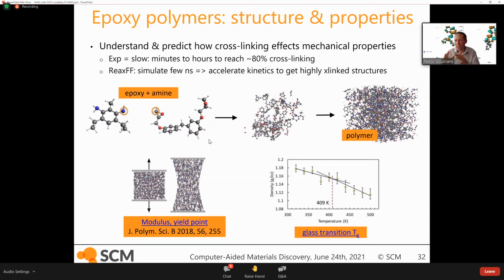And typically what you get out of that are pretty good cross-linking densities, and the mechanical properties, things like glass transition temperatures, are pretty good. So you can use these bond tracking or bond boost simulations to design different curing agents to get, for instance, higher densities or polymers with higher glass transition temperatures. You can see that the trends between the experiments and the simulations are in excellent agreement.